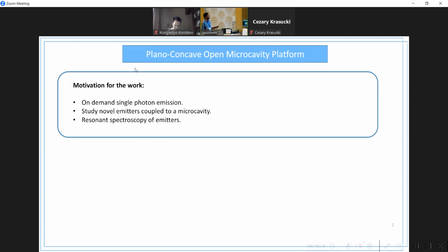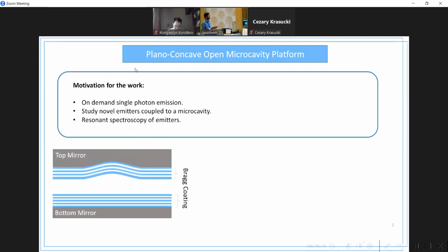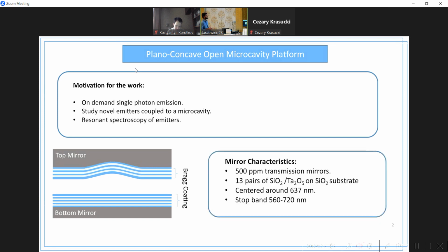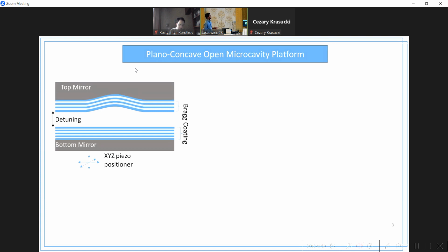So for all of that, we first need a platform. In my project, this is the cavity platform. It consists of 2 mirrors, a top and bottom Bragg mirror. The mirrors are designed in this experiment to be of 500 ppm, although we have others as well. There are 13 pairs of silicon oxide and tantalum pentaoxide on a silica substrate, centered around 637 nanometers, with a stop band from 560 to 720. Now, the bottom mirror lies on a piezo positioner, and we can tune the cavity length using the bottom mirror.